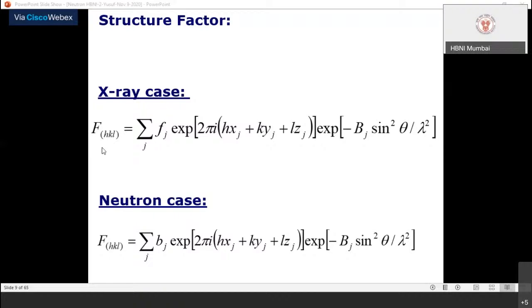The X-ray wavelength and the charge cloud dimension are of the same order. So the probe will see this extended form factor. And as you know, the form factor is always in Q space, and it is nothing but the Fourier transformation of the physical quantity in real space.